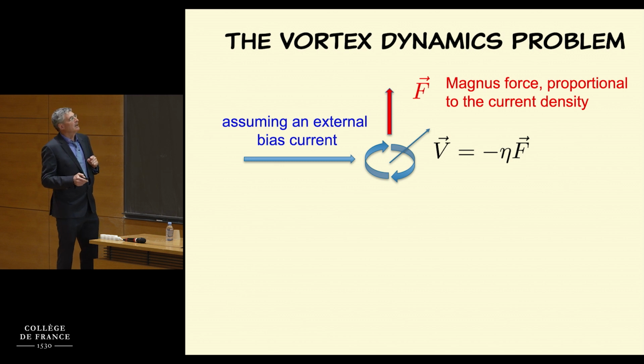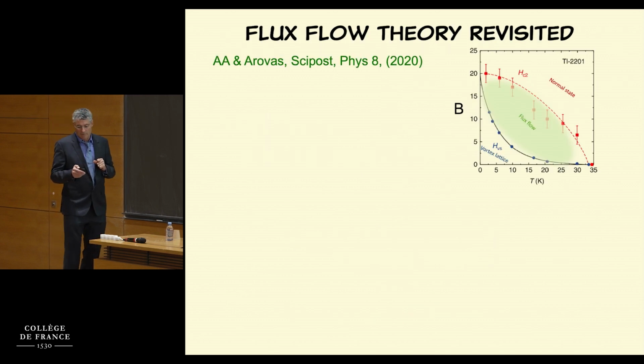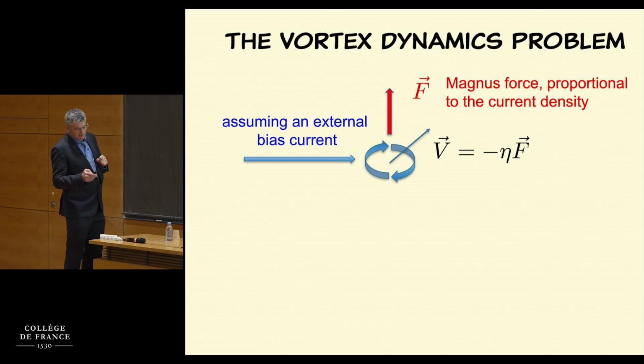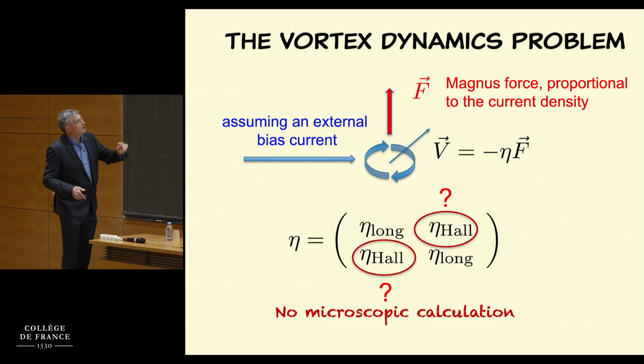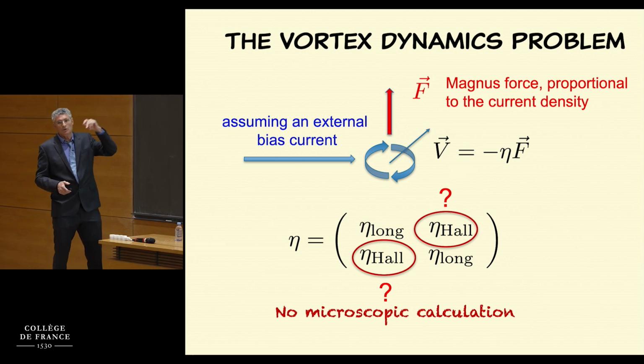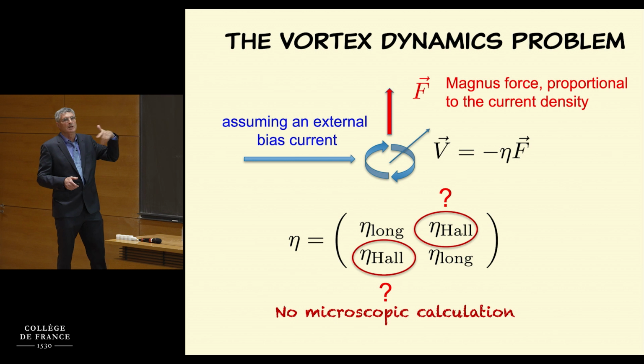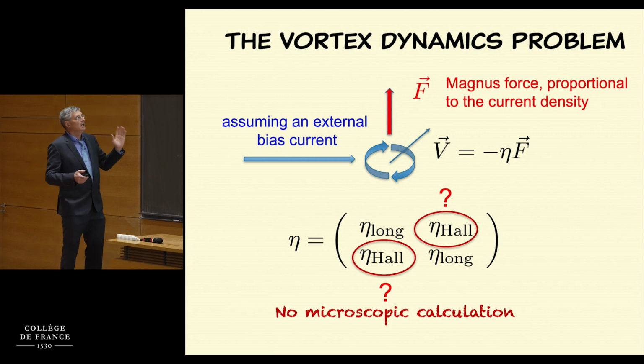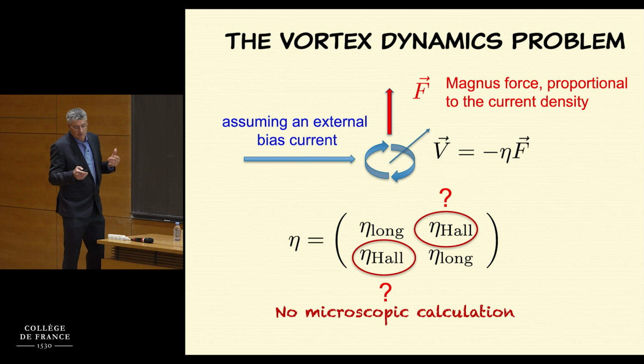The problem with eta is there's no microscopic calculation of eta. Okay, the longitudinal part you can relate to normal state properties by using Joule dissipation, because there's a dissipative response. There's heat generated from the diagonal part of the viscosity. But the off-diagonal part is non-dissipative. And if it's non-dissipative, one should have a microscopic theory to calculate it, like the Hall effect. It's not something that you can guess from other experiments.